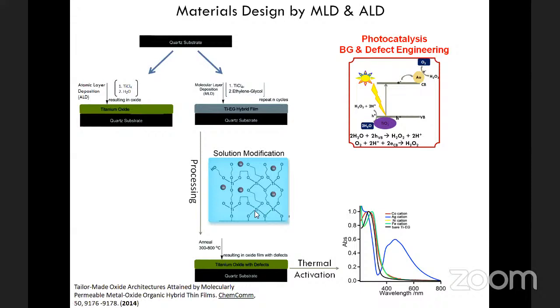And we take advantage of the fact that we first synthesize this amorphous titanium ethylene glycol hybrid film, which is permeable and can incorporate dopant atoms easily. And this was one of the first demonstrations of this methodology.